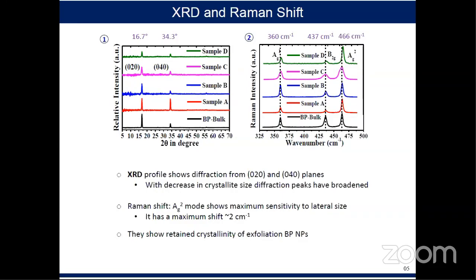That is due to the reduced crystalline size in nanocrystals. Again, in our Raman spectra in figure 2, we have compared the results with bulk. All the samples show three characteristic peaks, where the Ag2 peak is the characteristic peak for 2D black phosphorus. In case of any size reduction, this mode has maximum sensitivity. We found that this Ag2 mode for sample D, the smallest nanocrystals, suffered a maximum shift of 2 cm^-1 in Raman shift. So these two experiments suggest the retained crystallinity of the exfoliated black phosphorus nanocrystals.